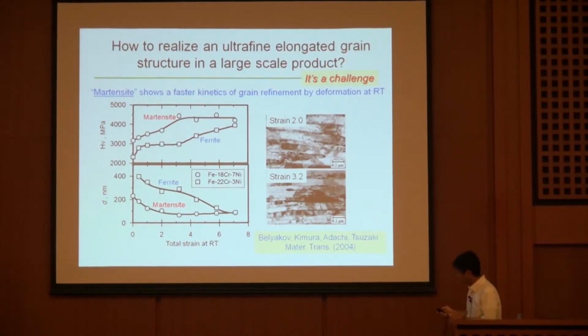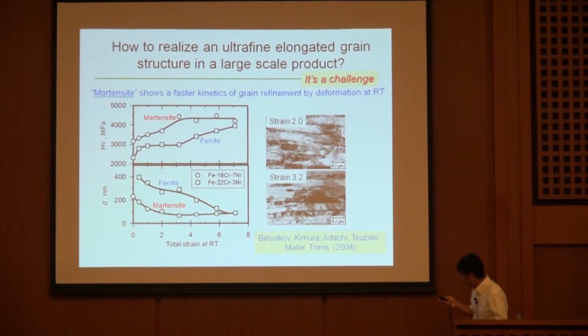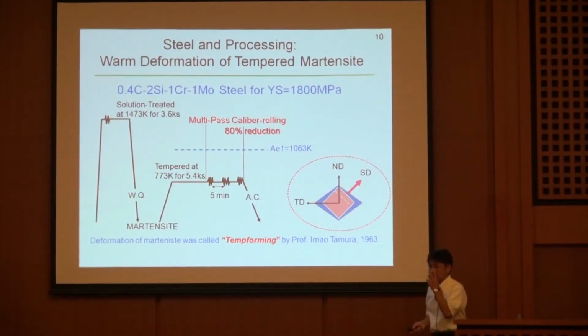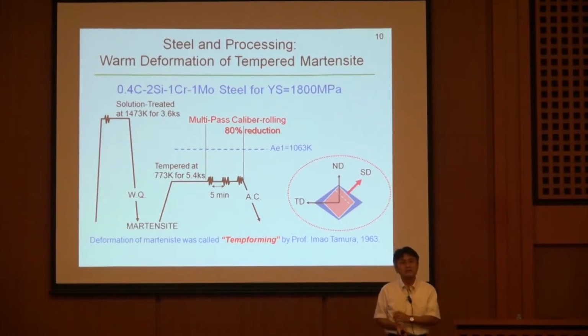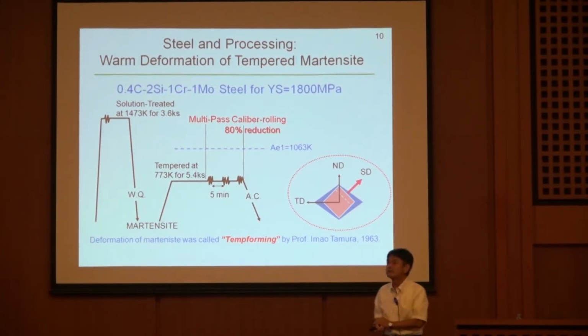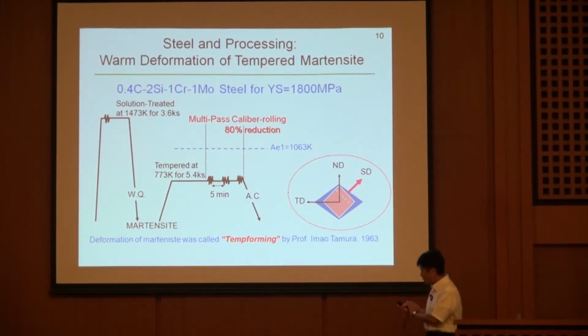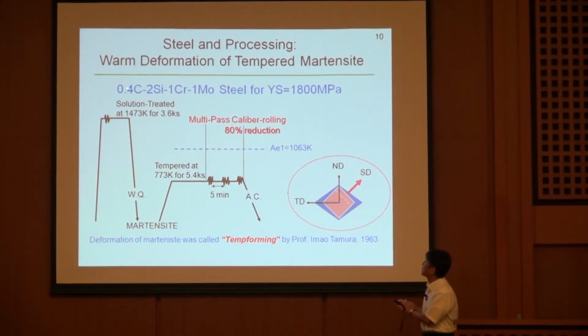So then we decided the chemical composition of the steel and the processing. The chemical composition is 0.4 carbon, medium carbon content, 2 silicon, 1 chrome, and 1 moly. This is necessary to obtain a yield strength of 1800 megapascal.